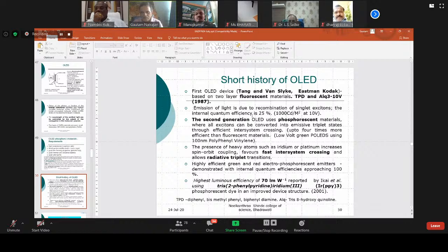I will come to the next diagram. Here the quantum efficiency is 25%. Means of 100% energy absorbed, only 25% is emitted as light. The intensity at 10 volts of this OLED is 1000 candela per meter square. Candela is a unit of intensity. Then phosphorescent materials are also used, where all excitons can be converted into emissive triplet states through inter-system crossing. So whenever you use the second generation, phosphorescent material, you can get very close to 100% quantum efficiency.